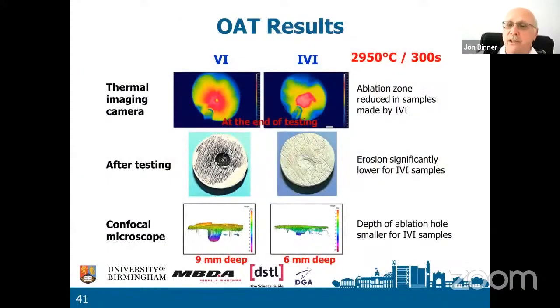These are some of the results. These are 2,950 for 300 seconds. This was comparing the old VI against IVI process, and you can see the IVI samples were much better. The depth of the ablation hole was smaller and the erosion was significantly less.